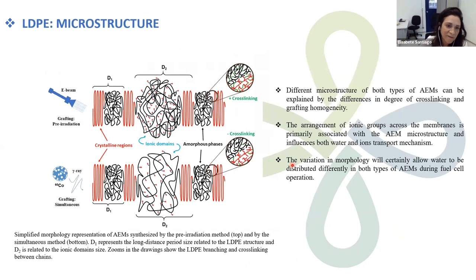We have also proposed a simplified morphological model for AEMs produced by both methods based on small angle X-ray scattering experiments. So we have observed a different microstructure of both types of AEMs that can be explained by the differences in the degree of cross-linking and the grafting homogeneity, as observed previously. And the arrangement of the ionic groups across the membrane is primarily associated with the AEM microstructure and is very important for water and ion transport mechanisms involved in solid electrolytes.